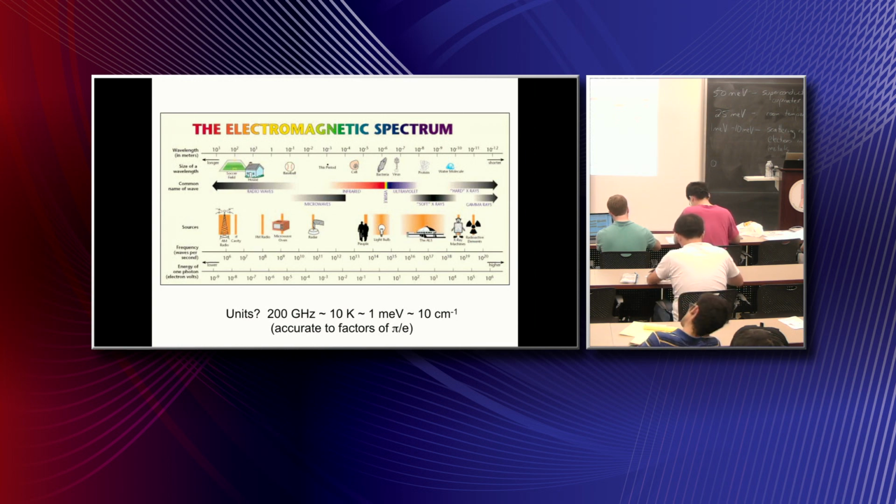And finally, let's put in as another final energy scale here something, let's say, 0.01 milliEV, which is the scattering rate in heavy fermion systems. Okay, so we're going to talk about those as examples of material systems where correlation effects are really at their strongest, if you will. And in such systems, one of the remarkable and amazing things is that a free electron description or free charge description is still valid, with some caveats. We have to imagine that the effects of interactions are all buried in renormalizing these free charge parameters, for instance, the mass. So in a heavy fermion system, the mass of the fermions moving along can be something like 1,000 times the free electron mass, so almost the mass of a proton.